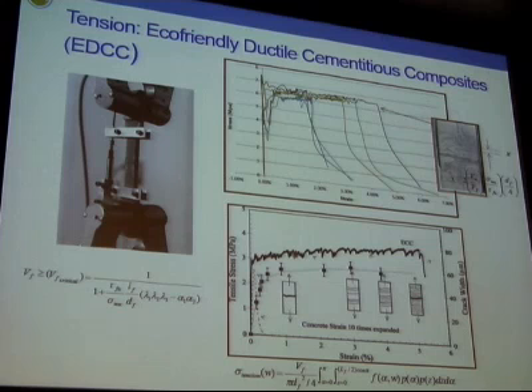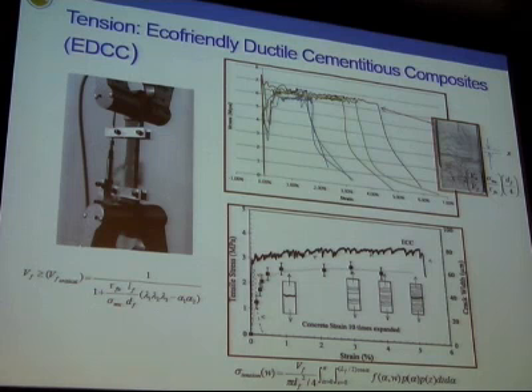The new class of materials that we are working on here is what we call eco-friendly ductile cementitious composites, and these have tremendous applications in earthquake engineering. So what you are creating is basically materials which have an elastoplastic response. So this is concrete, basically having an elastoplastic response. Normally, if you didn't have fiber reinforcement, this material would fracture here, and the load would drop very suddenly. But what we can do now, through micromechanical modeling, is get a material which has a very, very high energy absorption capacity, almost up to 5 to 6%. And this is quite exciting because now you can use these materials for a number of purposes.